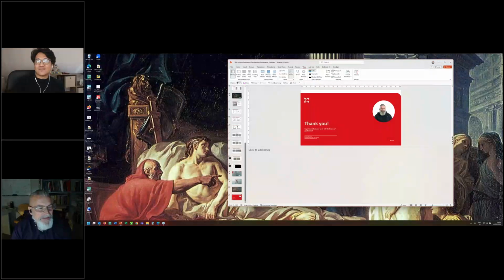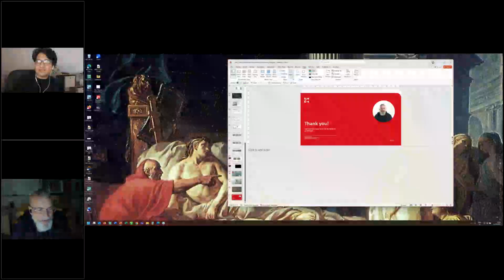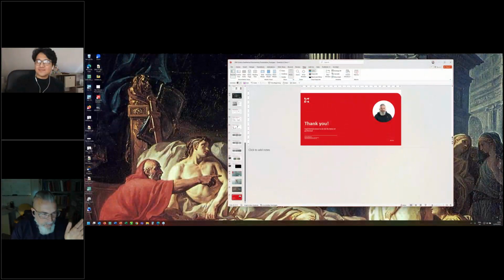We have done it at different CO2 concentrations, and what's very interesting, and this is something that we're working on as a capability, is looking at no CO2 and then intermediate CO2 and then high CO2, and then what we do is we take those 3 experiments and we calibrate a TOUGHREACT model that actually takes the silica scaling rate from the experiment and the CO2s, and then it can predict the actual silica scaling rate at various temperatures and CO2 concentrations, and it gives you exactly that sweet spot where the CO2 is just right for mitigating 95% of the scale or whatever.